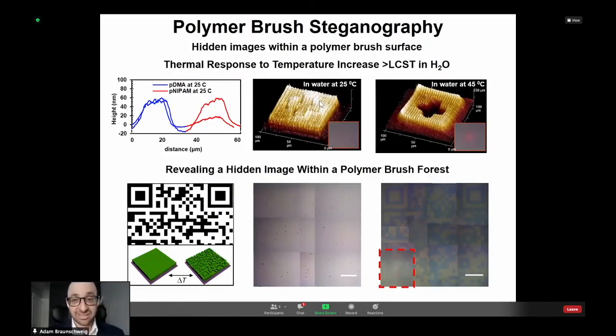So just as an example, he created this cross. And then when you heat this cross that's embedded, the cross is out of NIPAM embedded within DMA. You heat this up, the cross shows up. It turns out that the lower features show up brighter. You can see this cross here.